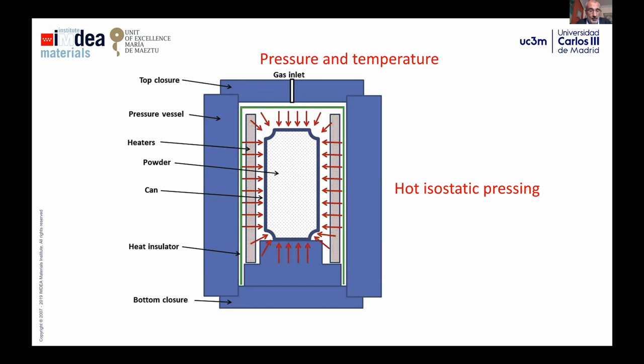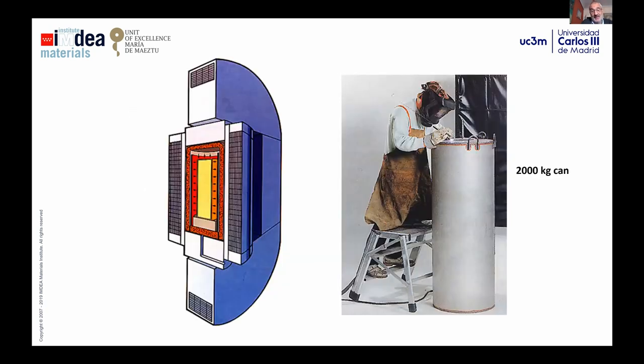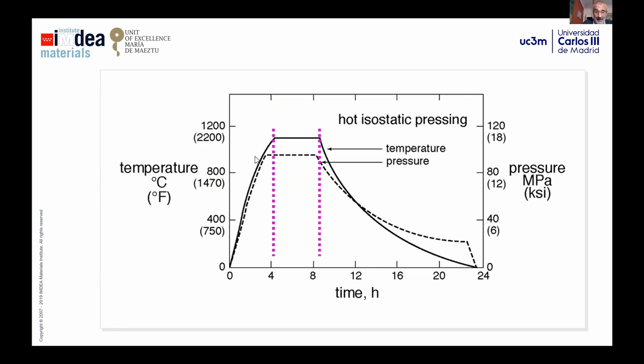By hot isostatic pressing, you put powders inside the can and you apply the pressure through a gas, and you can get at the end a fully dense material with a very homogeneous microstructure and, of course, very good properties, because you can control very well the chemistry of the powder and the microstructure of the final material. The problem of hot isostatic pressing is the price, because you need very expensive equipment to perform the pressing and the sintering at the same time. You usually have to can the powders inside the can, and this increases a lot the price of this method. Another important thing is that usually you need a long period of time to reach good properties at the end of the process.